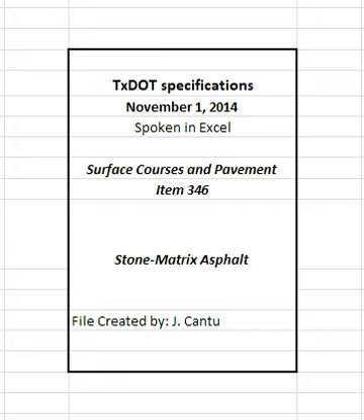4.4.2.1.14 Development of JMF2. Evaluate the trial batch test results after the engineer grants full approval of JMF1 based on results from the trial batch, determine the optimum mixture proportions, and submit as JMF2. Adjust the asphalt binder content or gradation to achieve the specified target laboratory molded density. The asphalt binder content established for JMF2 is not required to be within any tolerance of the optimum asphalt binder content established for JMF1. However, mixture produced using JMF2 must meet the voids in mineral aggregates, VMA, requirements for production shown in Table 7.